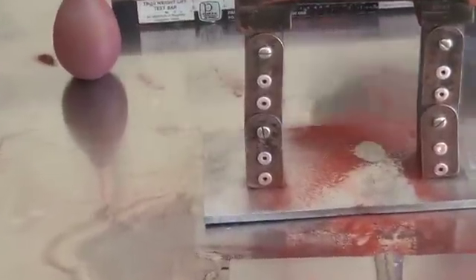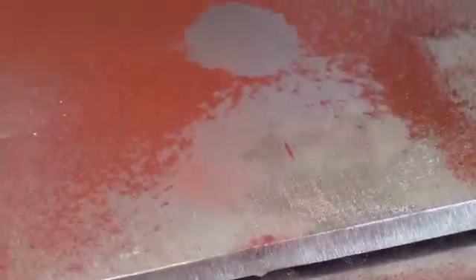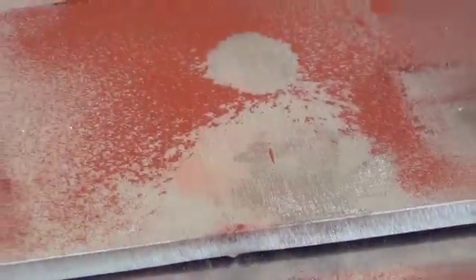Here is the indication in this plate, right at that location. The indication is about 6 to 7 millimeters long and it's very clear. I will now go to the second plate and do the same process.